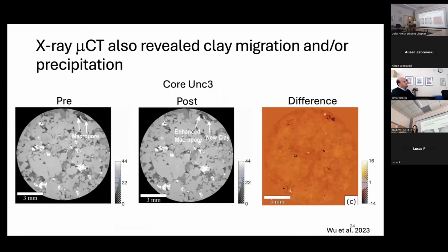Okay, well, back to your point, why in some of the samples we see porosity reduction. So this one, hopefully it's good enough to see. This is one of the uncemented samples. So it's a sample that lacks cement, but that doesn't mean it doesn't have it. It still has some, just less. If we just look at the black and white images right now, the dark ones are the pores. The different color refers to density, right? The darker the color, the lower the density is. So we see darker here, and then we see more darker area just above that.